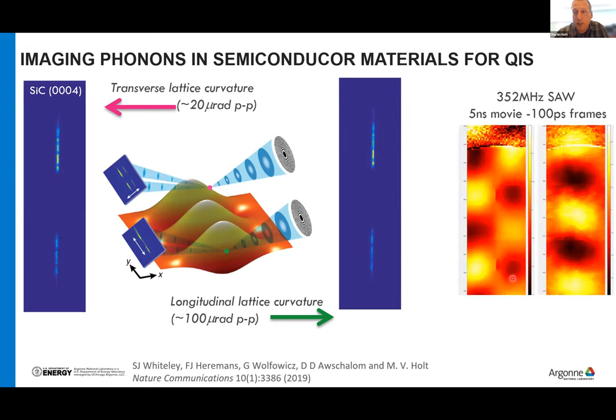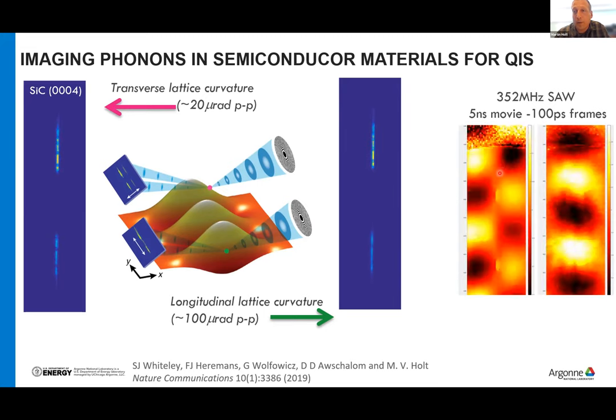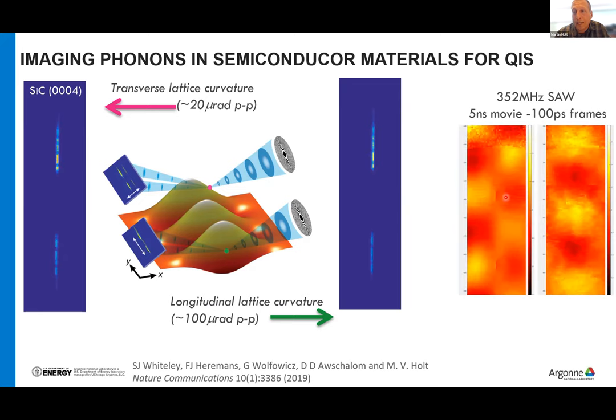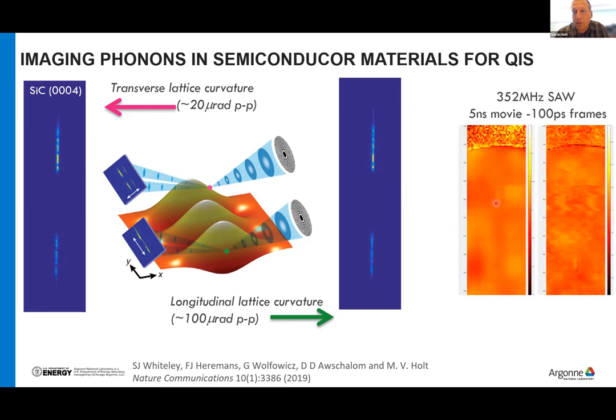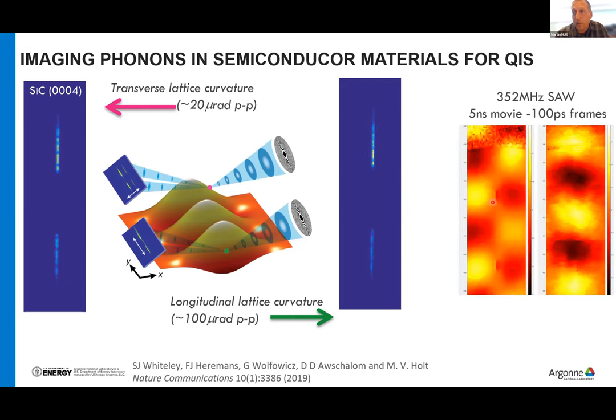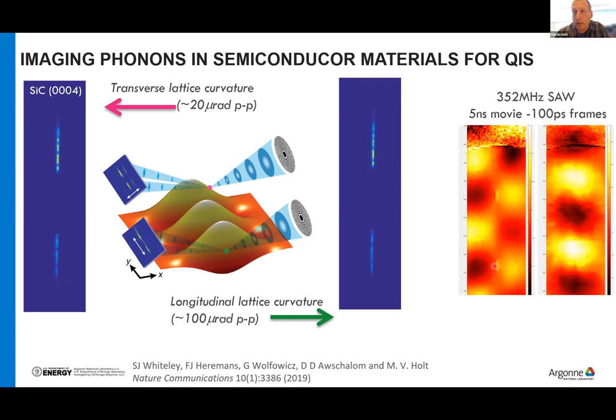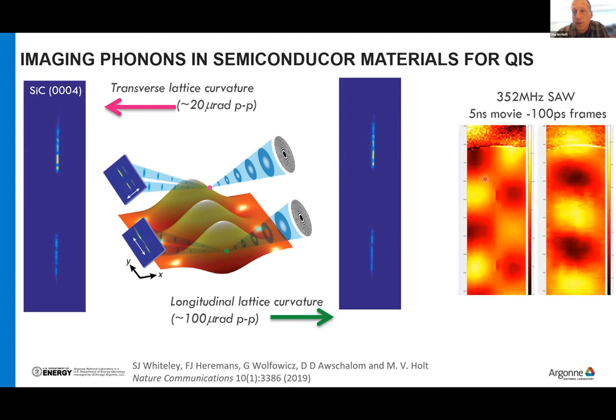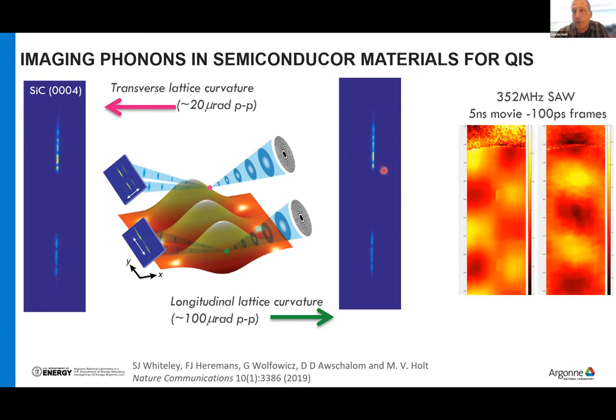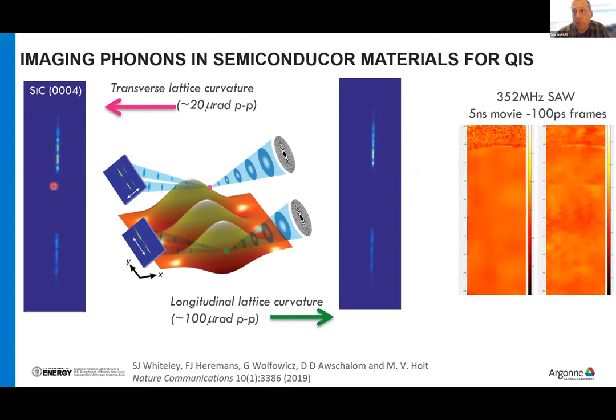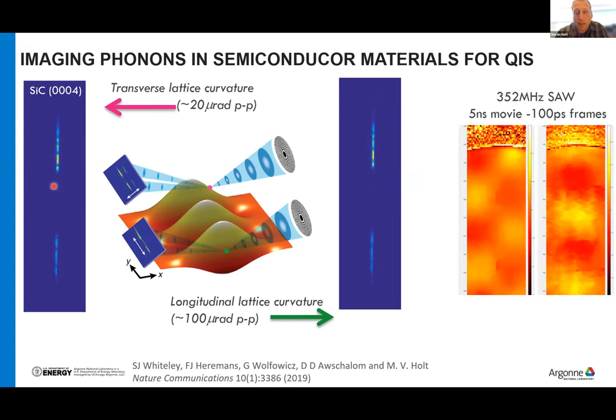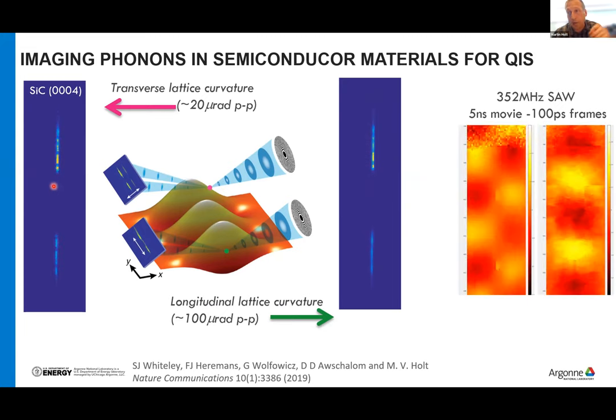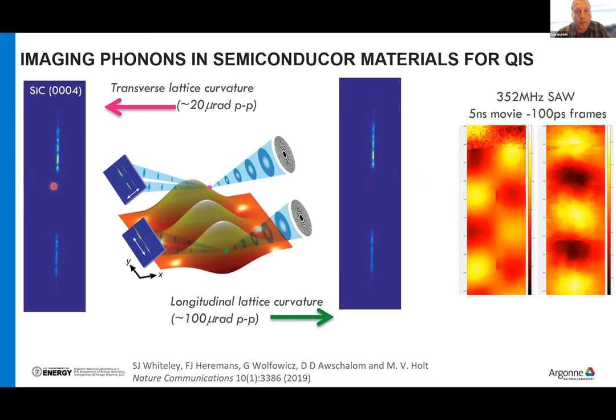But this lets you map out in real space, over this 20, 30 micron region, what this wave actually looks like and how it's interacting with the scattering structure that we put in here. It's this etch pit that we use for the photoluminescence measurements and to register everything. For each position in this map, you get a full time slice of two orthogonal vector components of strain. And that lets you use the material as a palette to understand the relationship.